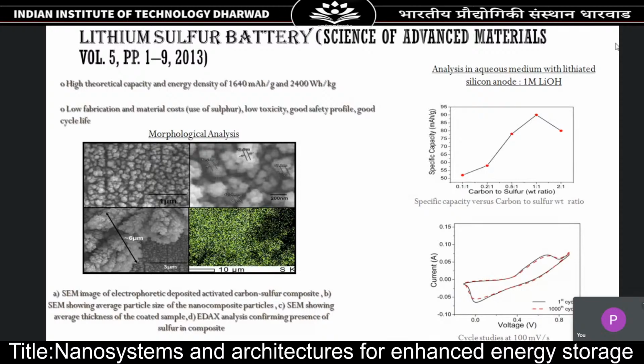You can see some of the SEM images of the electrophoretic deposited carbon sulfur composite. You can also see the EDAX analysis, which confirms the presence of sulfur. We plotted the specific capacity in milliampere hours per gram versus the carbon to sulfur ratio. You can see that there is an optimum ratio of about 1:1 when the specific capacity is the maximum. We also carried out cycling studies up to 1000 cycles, and there is very good fidelity of the device with very little fade.